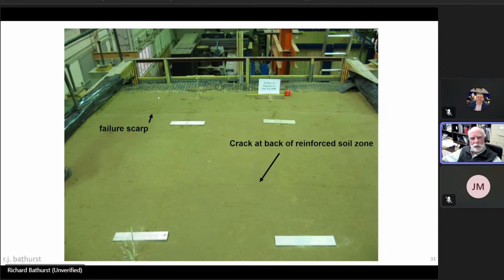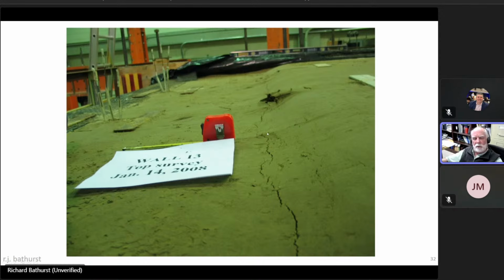At the front of this picture here, you can see the top of the wall, and you can see a failure scarp which has exited at the top of the wall, and you can also see a crack through the reinforced fill at the surface, which is located at the back of the reinforced soil zone, or if you like, the back of our equivalent gravity structure. And an oblique view gives perhaps a better impression. You can see the slump, as it were, and you can see the crack where the internal failure surface has propagated from the toe or heel of the facing up to the surface of the backfill.